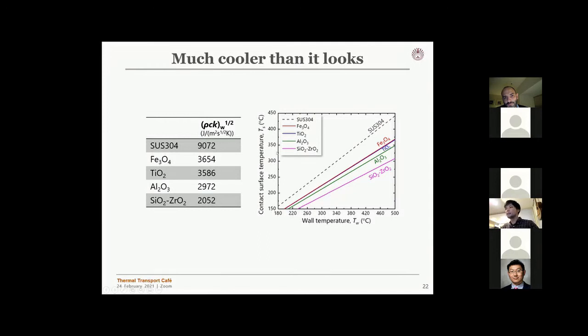But if you have an oxide layer material which has very poor properties, lower values of this property, you will have a huge temperature drop. If you take 420 degrees Celsius again, then you have a contact surface temperature of 250 or something like that. So there's a big gap between those two temperatures.